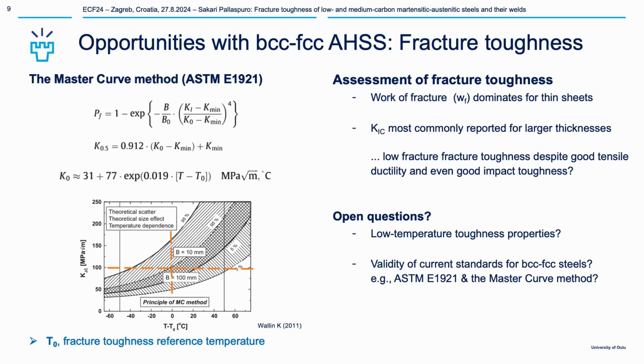In my presentation, the main assessment is the master curve method and ASTM E1921, and all of the standards and integrity procedures that follow these basic principles. For probability of failure, we know that it scales with the specimen thickness and this scaling factor. The median fracture toughness historically follows this temperature dependence around the temperature level where the specimens reach a thickness-corrected stress intensity factor of 100 megapascal square root meter.